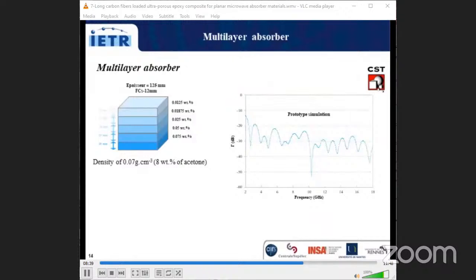The simulation of the absorption performance was first done using the CST software and the presented dielectric properties, and the thickness for this simulation is 125 millimeters. This thickness is chosen because it is often used for commercial multi-layer absorbers. This simulation predicts a good absorption performance with a reflection coefficient lower than -13 dB in all the studied frequency range, which means that more than 95% of incident waves are absorbed.